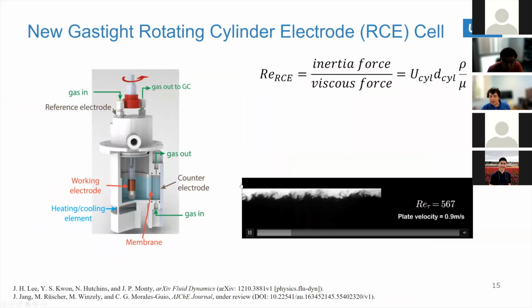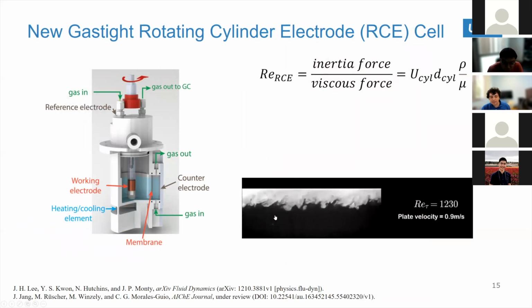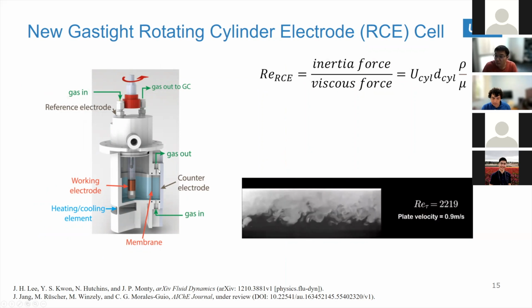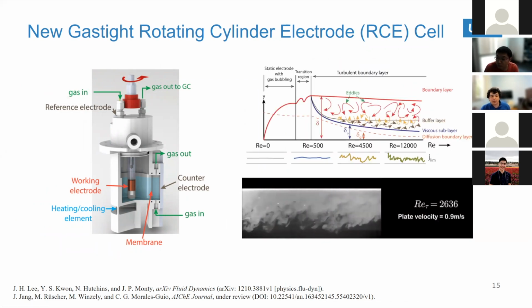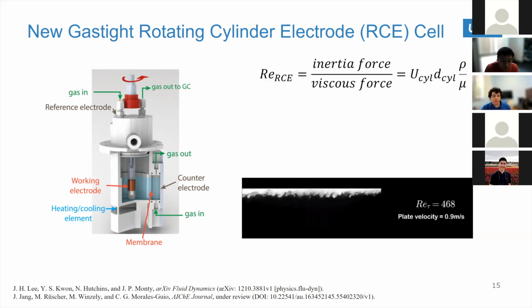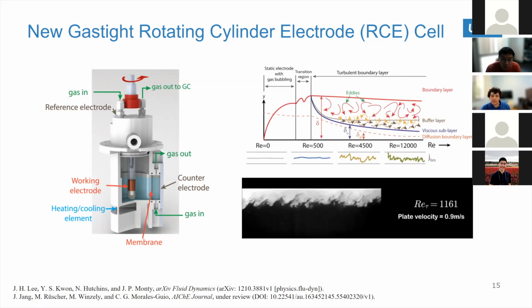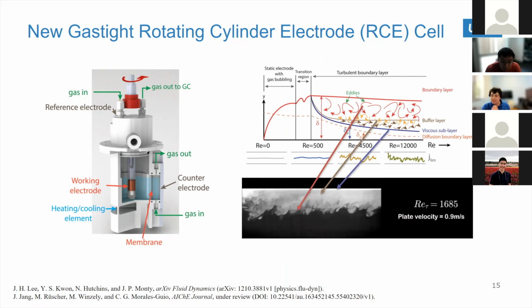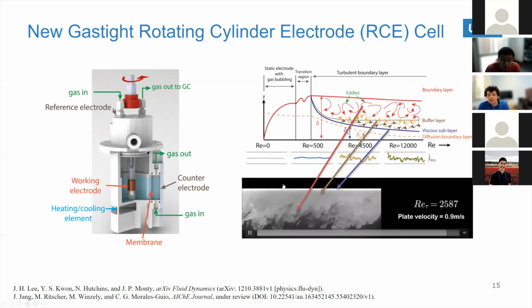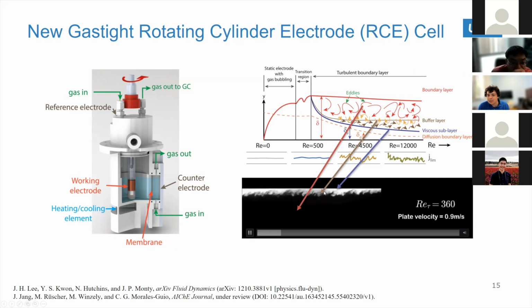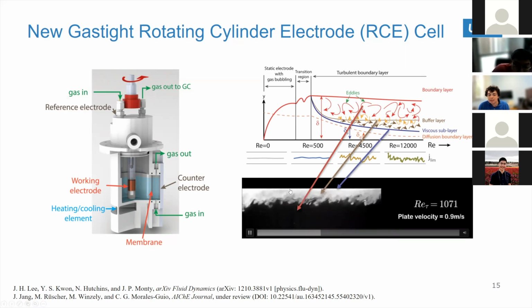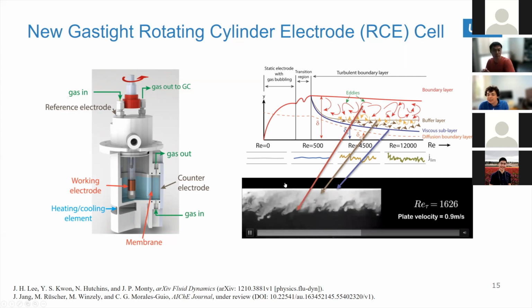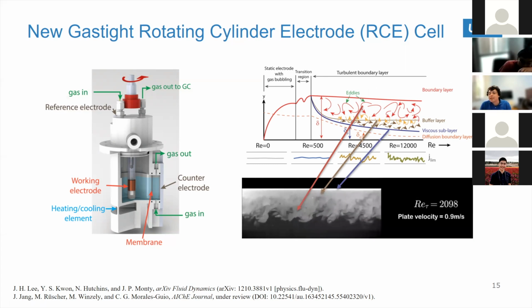The hydrodynamics of this type of systems were well described in the 60s and 70s. The rotating cylinders have been fully described. What is important to note is that we can use the Reynolds number to describe the turbulent regimes that we have in these systems. What is key to notice is that in any system, even if it's not a cylinder, if it's not rotating, what you will have at the surface of the electrode is a no-slip condition. That means the water in contact with the surface is viscous and does not move. It stays static at the surface of the electrode, creating a pocket that may help us explain why we see this CSTR type of behavior.